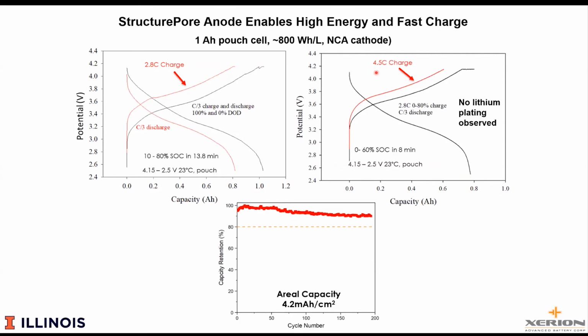The challenge remains capacity fade. What I'm showing you here is the usual typical best results, which shows 10% fade after 200 cycles. We get that some of the time. Other times we get catastrophic fade. And it's probably due to the swelling and deswelling that leads to mechanical damage within the scaffold. And so, that's a major area of work now in my group, is to try to understand how to mitigate and understand that so that we can reproducibly get a high capacity in the system.